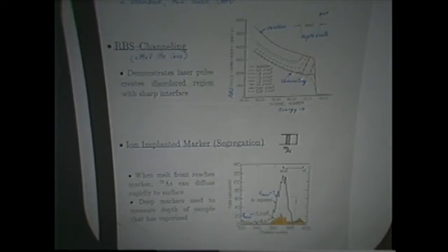Now we zap the silicon with a laser at different levels. And here are the different levels, and it's key-coded on the curves. Initially, we stay at the channeling direction. But as the laser energy increases, we get some disorder scattering. And the disorder scattering increases as the laser intensity increases. And it increases and it increases. Here, by the time we're at 1.2 joules per square centimeter, we have a sharp interface, and we get almost a random situation at the surface. That sharp interface moves as we go inside the crystal. The sharp interface suggested that we had melting, but we didn't really believe it.